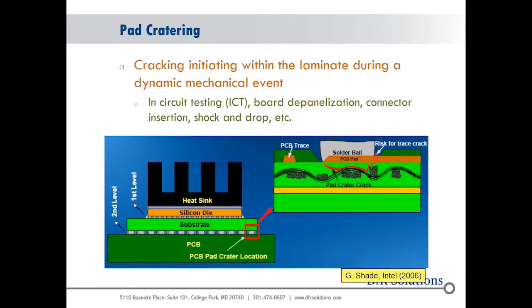Just definitions of pad cratering. It's crack initiation within the laminate during a mechanical event, such as ICT, and we talked about board depanelization, connector insertion, shock and drop. So that's pretty much the definition of a pad crater. The thing about pad cratering is, it's one of these failures that you may not see during electrical test. What will happen is if the trace doesn't crack here, this is still electrically functional.